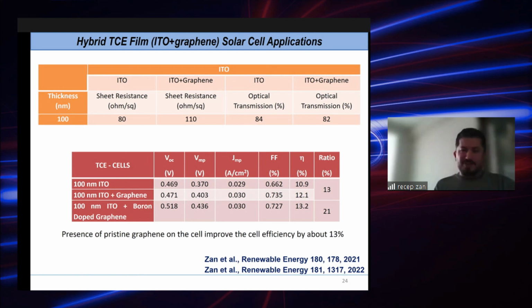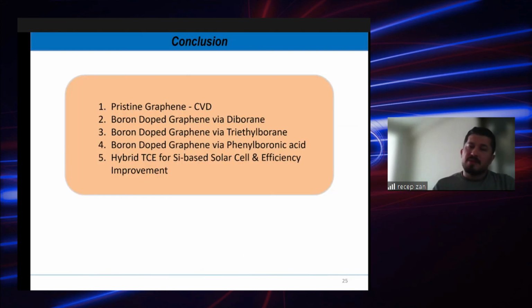Okay, I'm about to finish here. What I talked about was pristine graphene in a CVD system, boron-doped graphene using diborane, boron-doped graphene using triethyl borane, and boron-doped graphene using phenylboronic acid. If we compare the three, diborane is easy to use in a CVD system and it is much easier to obtain a homogeneous film, but triethyl borane and phenylboronic acid have advantages over diborane because we don't use any additional gas during their synthesis. And both pristine and boron-doped graphene were used in silicon-based solar cells along with ITO as a hybrid structure, and the cell efficiency improved well.